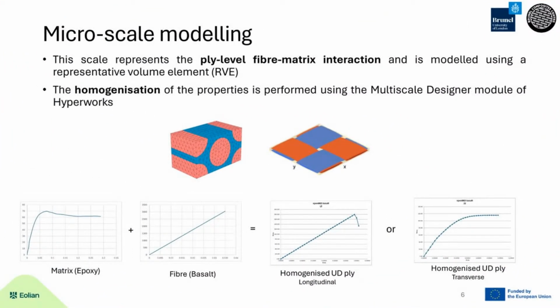So here I've shown a UD volume element or a woven fabric or any other representative volume element that we can choose, together with the vitrimer properties that we have extracted and the fiber properties, which are usually known from the data sheets and literature. So we take the properties of the matrix and the fiber, and we can homogenize them to get the properties of a composite ply, which can be UD or bidirectional or any other orientation. So this is the first, lowest step, the microscale modeling step done on the composite itself.